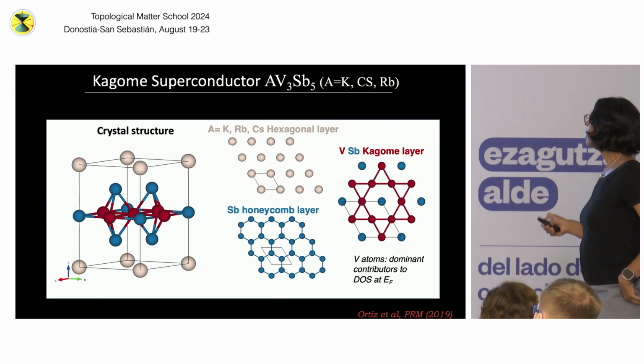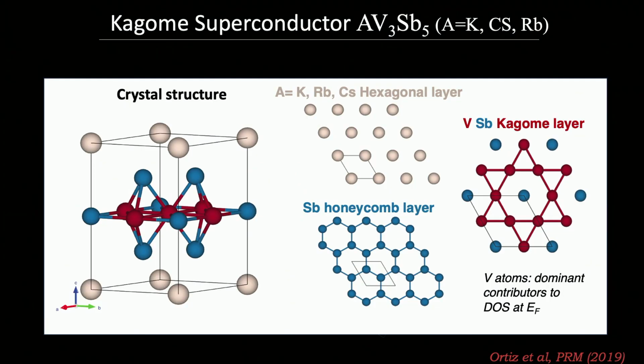Okay. So the material I'm going to be talking about is this 135 compound, and specifically the rubidium, vanadium, antimony, 135. It's a Kagome system. So you can see this is the Kagome plane right here. You can see it here as well. Right above, you have a honeycomb layer of antimony atoms. And above that, you have a hexagonal layer of alkali atoms. So hexagonal, honeycomb, and Kagome.